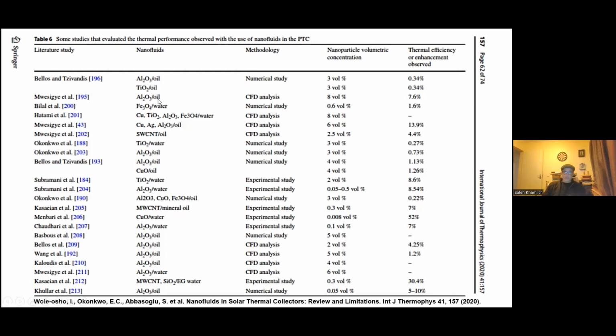Other scientists use aluminum oxide. They use what we call computational fluid dynamics analysis. At 8%, they found 7.6. Jumping quickly to some other scientists who are using experimental studies, like in this case or that case, where they use titanium oxide with water at 2 volume fraction, they found an 8.6 enhancement.